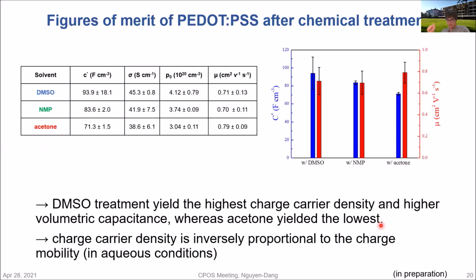As I mentioned earlier, with the AZ4000 photoresist, we can use several solvents, and I chose three well-known solvents, and DMSO is biocompatible. It showed that by using different solvents, we changed a little bit the mobility and the volumetric capacitance of PEDOT:PSS. There's an inverse proportionality between the capacitance and the mobility. Basically, with DMSO we have the highest volumetric capacitance, but we have the highest mobility with the acetone treatment, whereas the volumetric capacitance of the acetone treatment is the smallest.